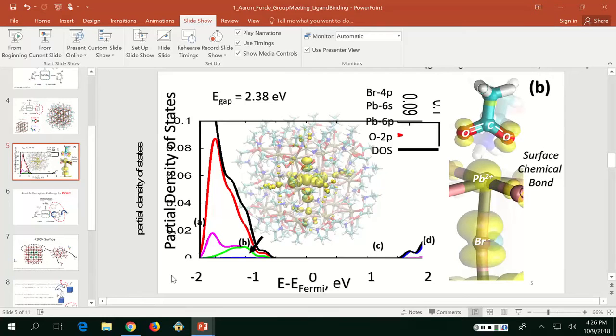But not to the... Oh, it's not inside the gap, though. So there's no localized state on the ligand. This partial charge density for HOMO shows that there is nothing on the ligand, everything is inside the gap. So it's very favorable for photoluminescence. Usually if you think there's any electron density on the ligand, it might be a trap state. But in this case, it's just hybridizing with the surface. So you can view it as part of your 1s wave function. Oh.